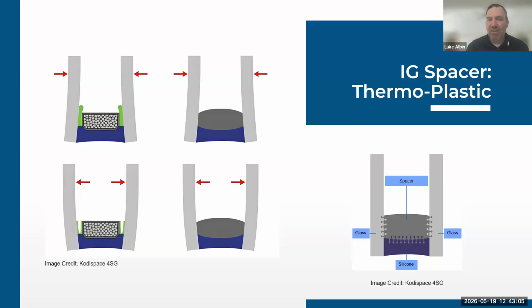The thermoplastic spacer, that's actually one of the big selling points for the manufacturers of the thermoplastic spacer: gas retention. They are saying less than 1% per year. Some naturally absorbs into the material itself. But when you look at the warranties of the thermoplastic spacer versus the metal spacer, on the commercial side of things, typically you'll get a 10-year seal warranty. Thermoplastic is 20 years. They've done advanced testing of 40 plus years, so that might even bump up. But take a look at the warranties, and regardless, they typically won't warranty against gas loss. But that's what should be expected. I know that's a pretty long-winded answer, but anywhere between 1 and 3% in a typical windows scenario.